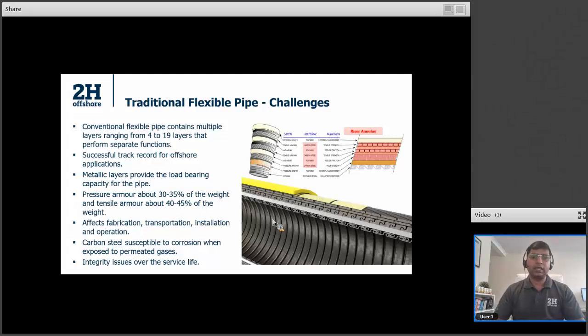Further, the carbon steel is also susceptible to corrosion when exposed to permeated gases, causing integrity issues. It's also interesting to note that while these carbon steel structures provide the required strength, there's different variations possible for these carbon layers to suit the required field conditions. And the harsher the environment, you need a grade of steel which can accommodate the permeated gases. But unfortunately, this leads to a thicker grade of material, and this causes additional weight onto the pipe structure, which is also a disadvantage, especially if you're looking for deep water applications.